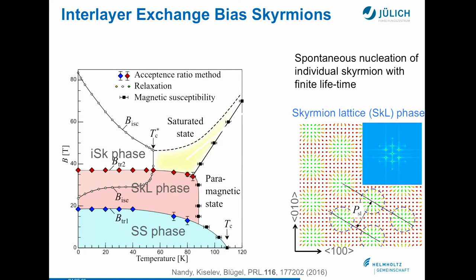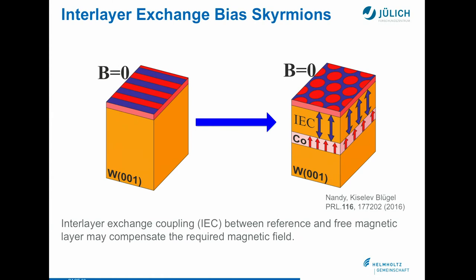These small skyrmions you can achieve, but you need magnetic fields in the order of 30 Teslas. This is not exactly what you want to have in a device, so you have to get rid of these Teslas. Therefore, we have the following suggestion. What we do is an interlayer exchange structure. So you have the tungsten. You slide in a certain cobalt layer, which is ferromagnetic and polarizes the tungsten material. And this polarized tungsten material exerts an internal magnetic field on the magnetically active manganese layer.